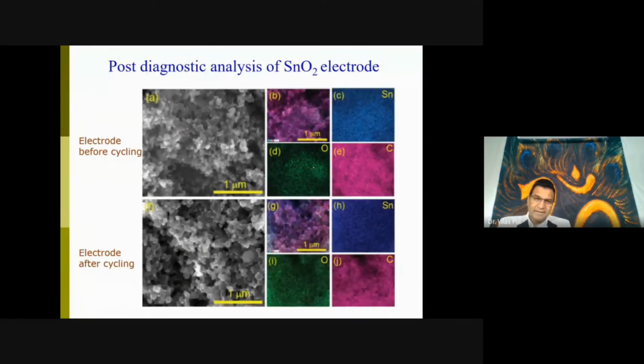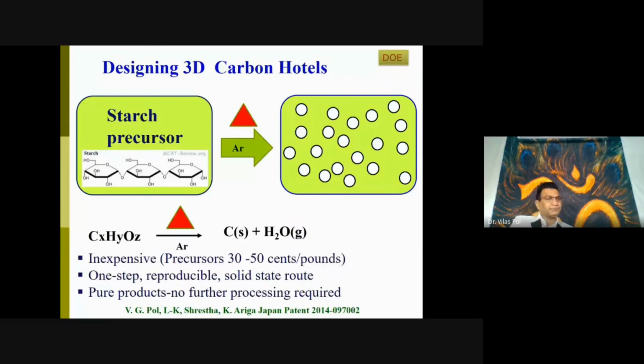We open up the battery and see what happened inside the material. What you can see is that the electrode which we had inside the battery, which had some cavities, still has those cavities after cycling. That means that the architecture does not degrade or decompose because of continuous charging and discharging.